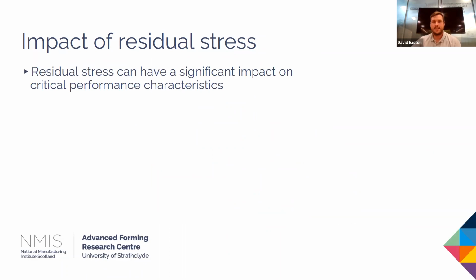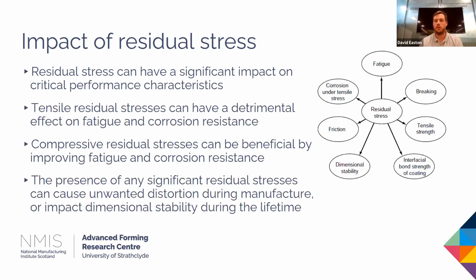Residual stress can have a significant impact on critical performance characteristics. So I'm not going to go into much detail here in the model. We actually did a webinar last year taking a more in-depth look at residual stress, where you could find some more information on this. But it's enough to say just now that tensile residual stresses, for example, could have a detrimental effect on fatigue or on corrosion resistance, whereas compressive residual stresses could be used to improve fatigue. And any residual stress, whether it's compressive or tensile, desired or undesired, can result in distortion. And that's a particular focus for us here at the AFRC.